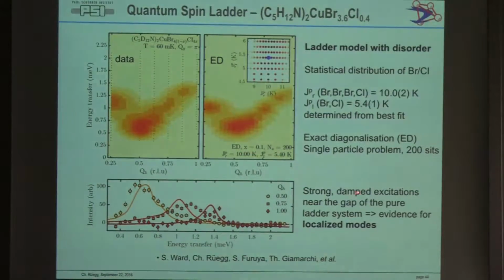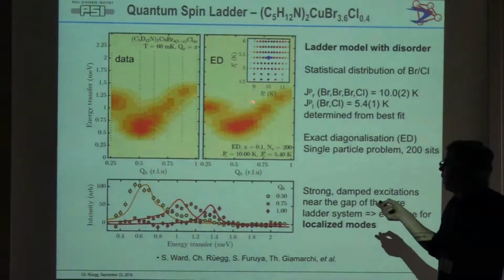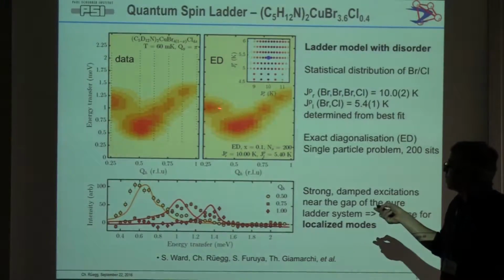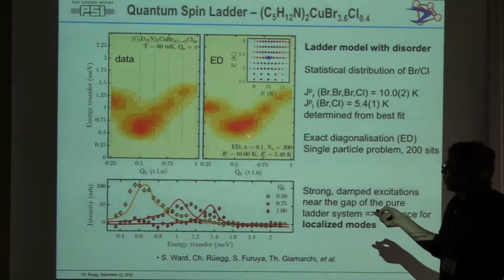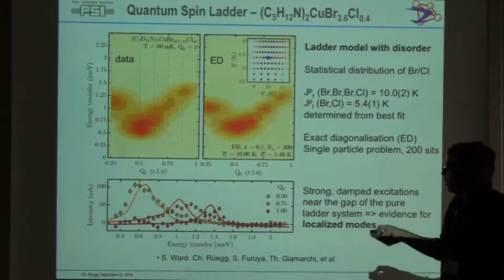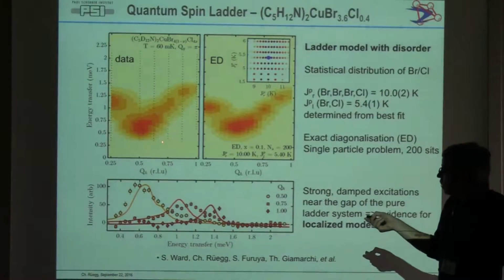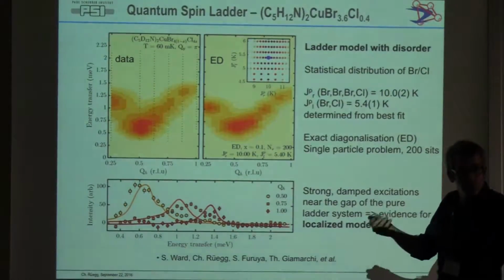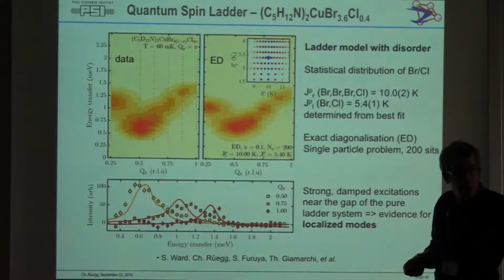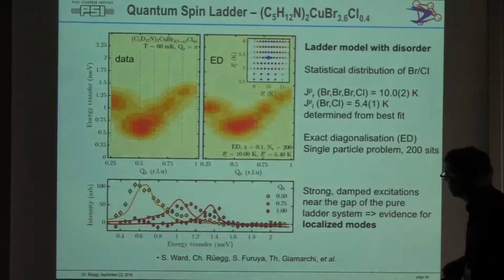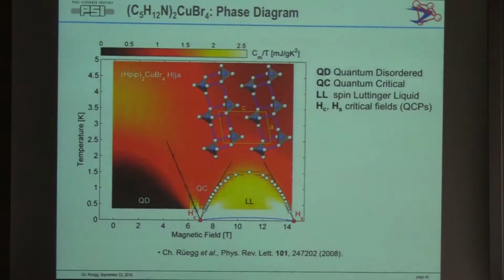So here you see some examples of the data, now convoluted in this case also with resolution and so on. And on the right you see a calculation with exact diagonalization. And if you do this kind of disorder effects, what you find is that you get an indication of localized modes which appear below the excitation gap and so on. So we can now play also with this kind of chemical route to introduce disorder and see interesting effects there. Yes, so I think with this picture I could stop now.